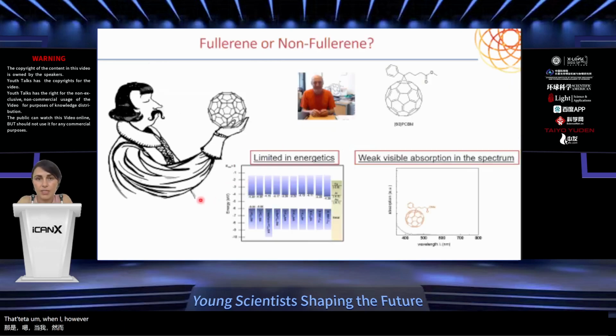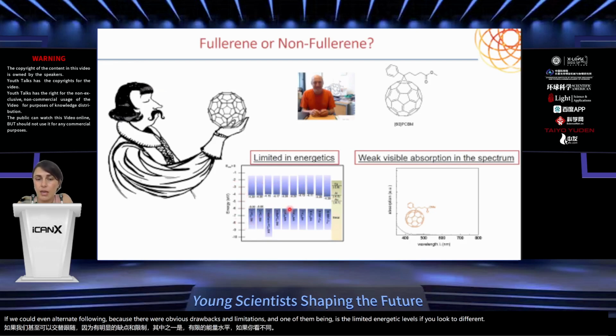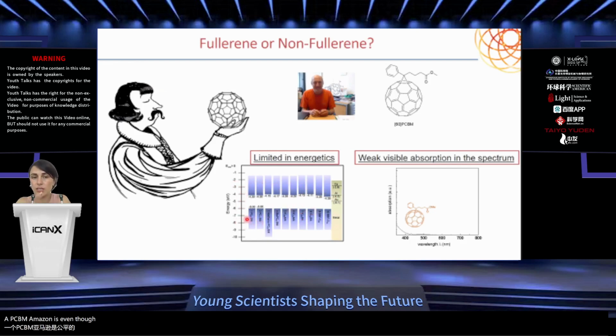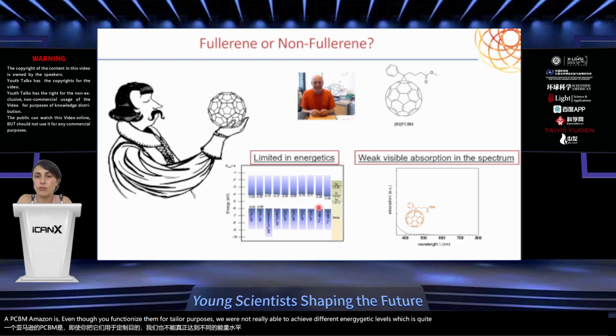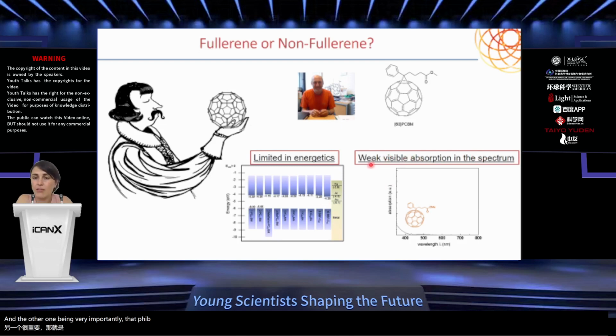When I, however, finished my PhD, we started to think maybe we should take a step back and think if we could even alternate fullerene, because there were obvious drawbacks and limitations. One of them is the limited energetic levels. If you look at different PCBM derivatives, even though you functionalize them for tailored purposes, we were not really able to achieve different energetic levels, which is quite important for the photovoltaic performances. And the other one, very importantly, is that PCBM had a very weak visible absorption in the spectrum.